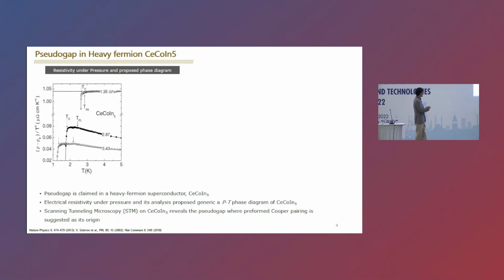For example, in the heavy-fermion compound cerium cobalt indium-5, Vladimir Sidorov and the Los Alamos group reported electrical resistivity as a function of temperature. Here, the y-axis is rho minus rho 0 divided by temperature to the power n. What he noticed is that right above the superconducting transition temperature, there is a deviation from the high-temperature scaling, and he noted the possibility of a pseudogap.